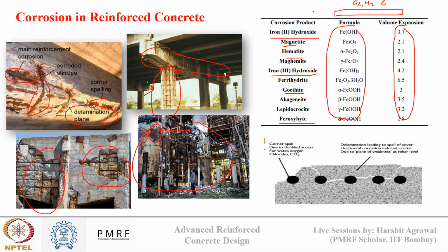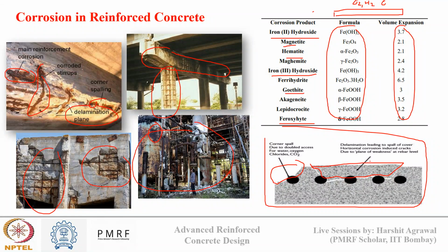Okay, and this image shows what is happening. So this is spalling of cover. Complete cover has been chipped off from here, and this is known as delamination. So between my concrete and steel, I have lost the bond. That loss of bond is known as delamination of the cover concrete, and this is happening because of formation of expansive rust product inside concrete due to interaction of concrete with the environment as the passive layer breaks.